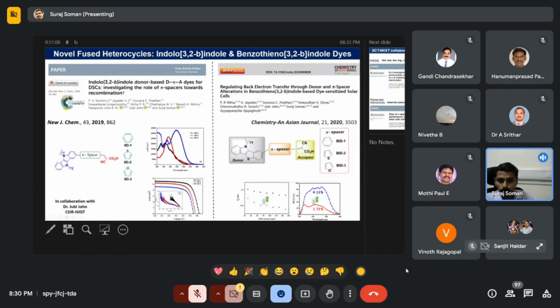Here, the moment you change the donor, the furan actually starts performing better because there is a twist that happened in the molecule with the introduction of the furan. So that coupling between that donor and that particular pi spacer made some changes in that twist, the dihedral angle between the donor and the pi spacer. And that actually helped in improving the performance.